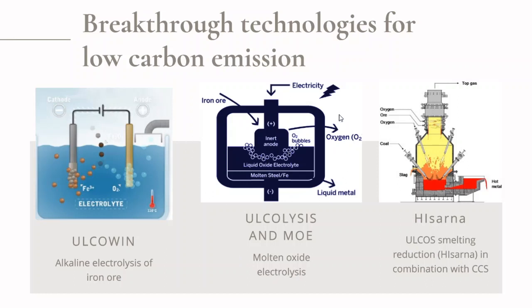The HIsarna process consists of a reactor maintained above the melting point of iron throughout the vessel. In the cyclone, the temperature is further increased by adding pure oxygen, which reacts with carbon monoxide present. The iron ore melts immediately and drips to the bottom of the vessel, where powdered coal is injected, converting the oxygen from iron ore to bind with carbon, thus producing pure liquid iron.